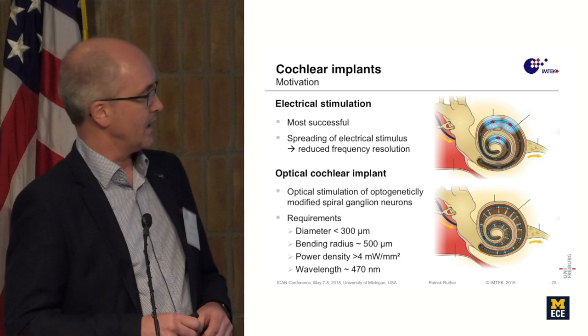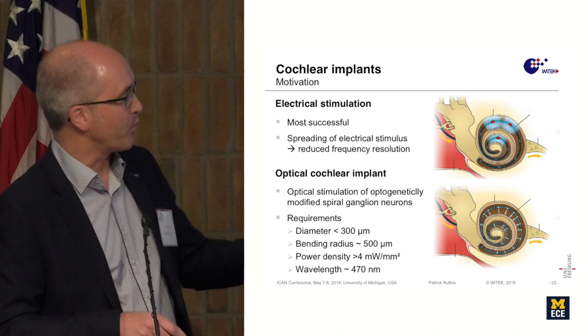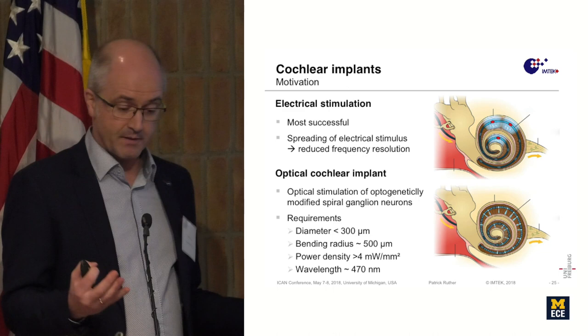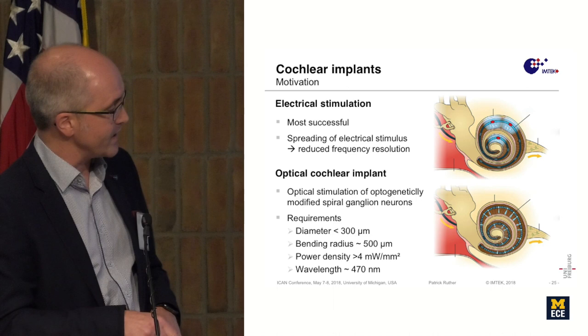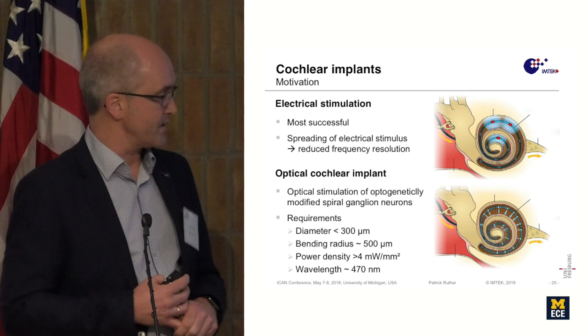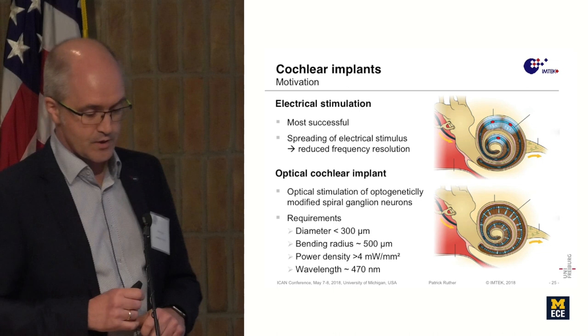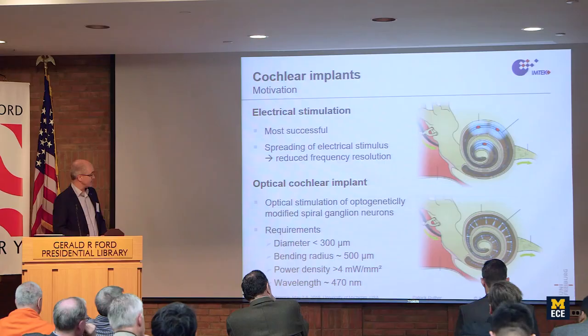So nowadays, I will show the picture later, we work with large animals, but typical numbers are here. 300 microns diameter of the probe when it is encapsulated. We need bending radii around 500 microns. Power densities, as we know it from optogenetics, 4 milliwatts per millimeter squared, and as channelrhodopsin 2 is used, a wavelength around 470 nanometers.